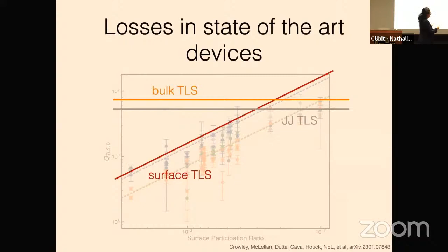Okay, if I have to plot the course forward now based on this plot, I would say this is interesting because this loss is about an order of magnitude higher than what Rob has measured with the dielectric dipper. And even though we're looking at the same sapphire nominally, one possibility is that you're actually dominated by a damage layer near the surface of sapphire that comes from polish damage or something like that. That's about 1/10 of the total thickness of the sapphire.